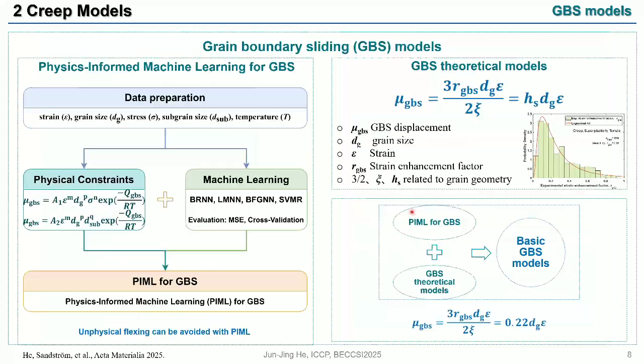To model the grain boundary sliding, we proposed a physics-informed machine learning, and here is the flowchart. First, it starts from the data preparation. We consider the different variables such as the strain, grain size, and the substructure. By incorporating the constraints with the machine learning algorithm, we can generate the final physics-informed machine learning. On the other hand, the theoretical grain boundary sliding models were also analyzed. By combining both, we can generate the final basic grain boundary sliding model. It is finally in a very straightforward form. It's proportional to the grain size and the strain, and all parameters here are well defined.